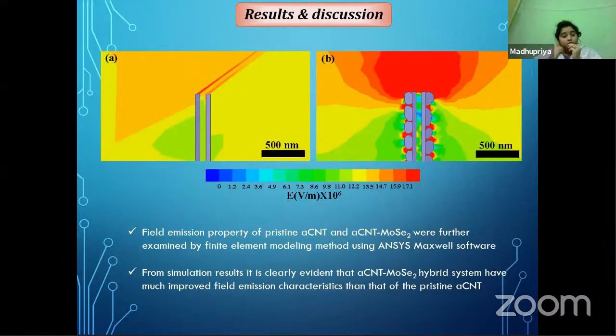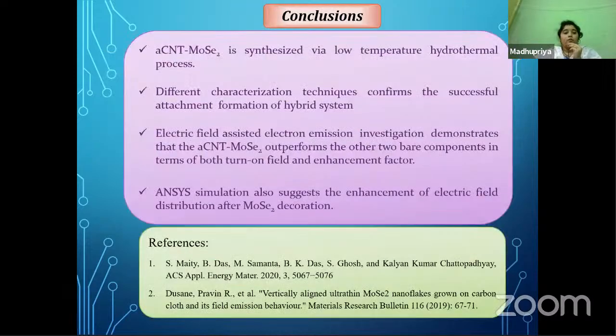We have also simulated these nanostructures with the ANSYS Maxwell simulation package. It is evident from the two images showing the electric field distribution around the structures, one for bare ACNT and another for MoSe2 decorated ACNT. A dense electric field distribution is observed in the case of the MoSe2 decorated system, and we applied almost the same parameters as in the experimental measurement.